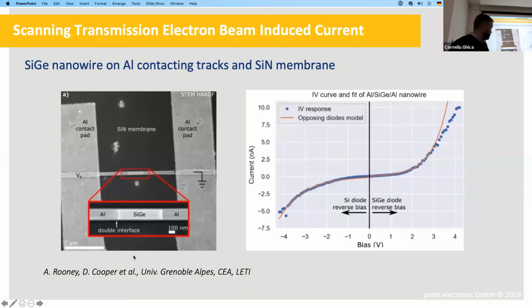And this is again work done by the same group, and they just submitted it to publish. So I will not show all their very lovely high resolution images. I will just go through it very quickly. In the TEM, the great advantage compared with the SEM is that you can get high resolution structural information. So we can see these 2 interfaces are not the same. You see they are different, and they have gone into high resolution analysis to investigate what these interfaces are.